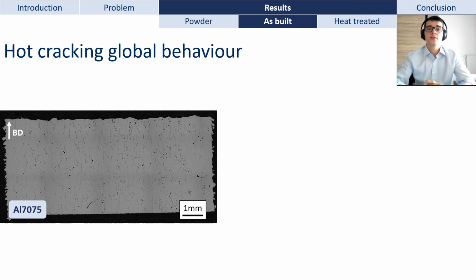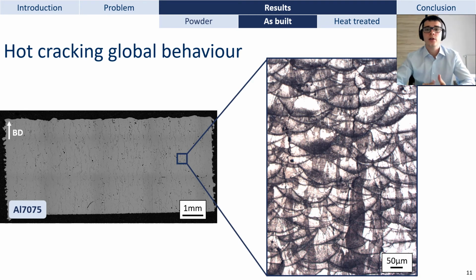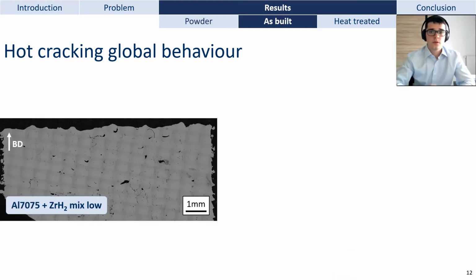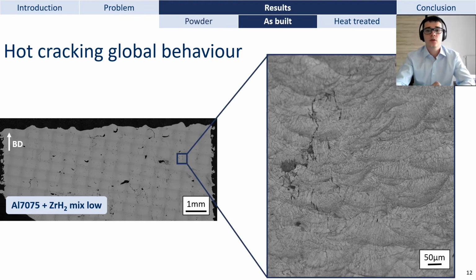So now let us look at the cracking behavior of these four alloys. Firstly, the aluminum 7075 that you have already seen at the beginning of the presentation exhibits a lot of cracks. We can link that with the elongated grains exhibited in the optical pictures of the etched samples. By using the linear intercept method, it was possible to approximate the mean grain size at around 40 micrometers. For the low zirconium content mix, the zirconium managed to reduce the amount of hot cracks. However, it does not manage to suppress hot cracking completely.